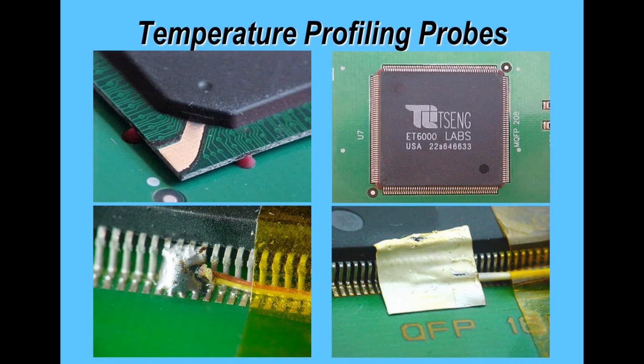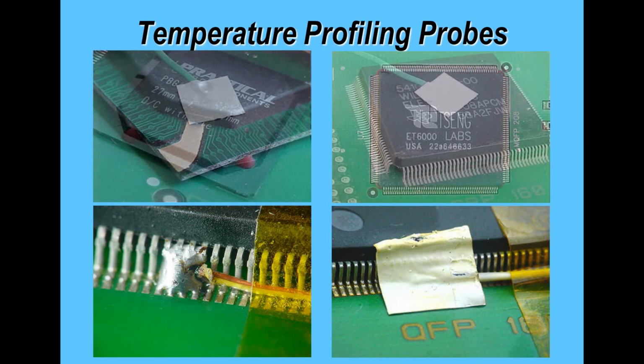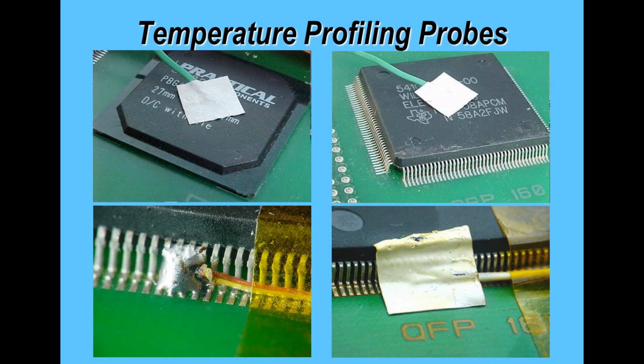Alternatively, some companies like to use aluminium tape, and you can see an example here where we're using aluminium tape to hold the thermocouple bead onto the junction, and that will last for quite a few profiles if you wish to use it repeatedly. If you're going to be mounting thermocouples onto the top side of packages, again I would use aluminium tape. You can use epoxy resin, but I find the aluminium tape works better. It transfers the heat and doesn't allow the thermocouple to lift.